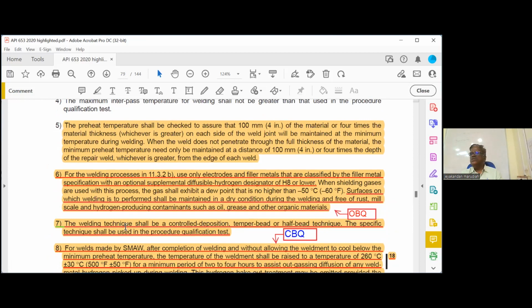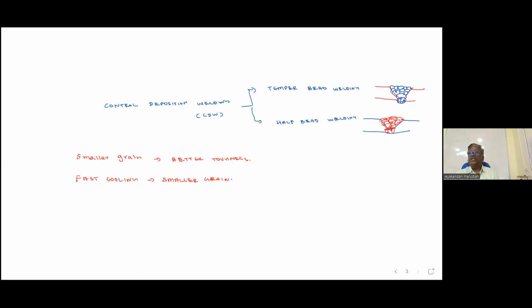See, what is a low hydrogen electrode? Which electrode is considered low hydrogen? E7018, 7015, 7016. Okay, very good. We call E7018, 5, 6 also the same. Normally we are using 7018. What is meant by low hydrogen? How much hydrogen is allowed in 7018? We are telling low hydrogen, so what is the maximum hydrogen allowed in this electrode? It is 15 ml per 100 gram of weld.